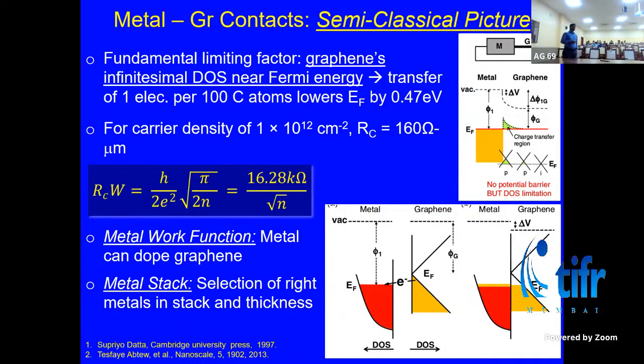At the same time, the world was also talking about the quantum limit and what kind of contact resistance one can achieve, say in the case of graphene. For instance, this number was quoted: 160 ohm micrometer. The fundamental understanding was that you bring metal in contact with graphene, and because of the difference in the density of states and the amount of charge present, the charge will transfer from graphene to metal, and hence a depletion will be formed. In graphene, if you lose one electron per 100 carbon atoms, you are going to reduce the barrier to 0.47 electron volt, and that's a big barrier to cross for electrons to move from the metal to graphene. That introduces the Schottky barrier, and hence the contact resistance when you try to conduct.